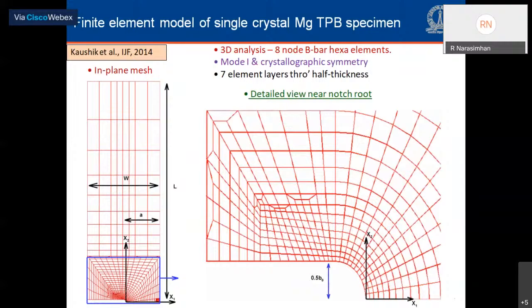This is a finite element model of the single crystal specimen. We did 3D analysis, and because in all these specimens, all the orientations, there is both crystallographic symmetry as well as mode 1 symmetry, we consider half the specimen through the thickness and half along the length.